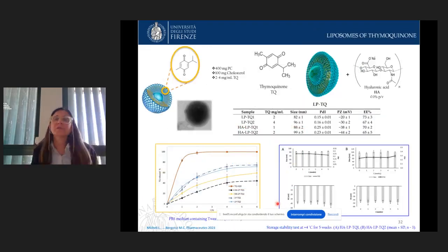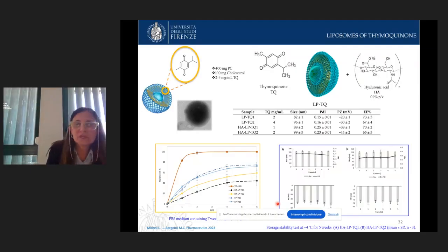Another formulation developed for thymoquinone delivery was the liposome. In this case, we used phosphatidylcholine and cholesterol for the preparation of liposomes, but we also developed liposomes where the bilayer was coated with hyaluronic acid. Hyaluronic acid is a biocompatible polymer with gelling properties, adhesion characteristics, and also anti-inflammatory properties. We developed 4 formulations with different amounts of thymoquinone, 2 liposomes without the coating and 2 liposomes with coating.